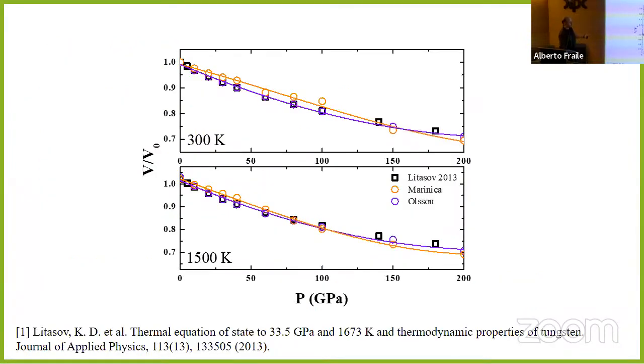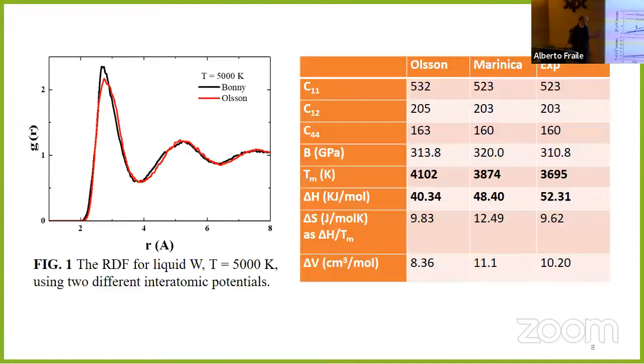So just to benchmark the potentials, we did a few simulations and tests. This is, for example, the equation of state. We present here the volume versus the pressure. And we compare the simulations with Marinica and Olsson to the theoretical work presented in this paper. And in both cases, the agreement is fair.